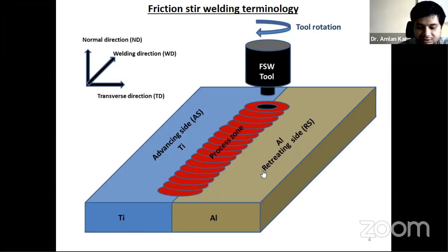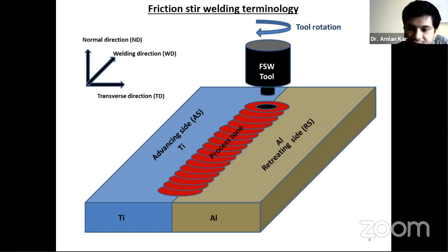When the shoulder touches the surface, you are not plunging further. So after that, what are we doing? We start traversing the tool along the interface. Because of the friction generated between the tool and the material, there is an increase in temperature, a friction-generated temperature evolution. You can see there are two materials, material 1 and material 2. Depending on the deformation behavior of each material, the actual shear stress developed on the material varies. In simple terms, if the temperature is very low, what will happen? It is difficult, and the tool material is subjected to wear and tear.